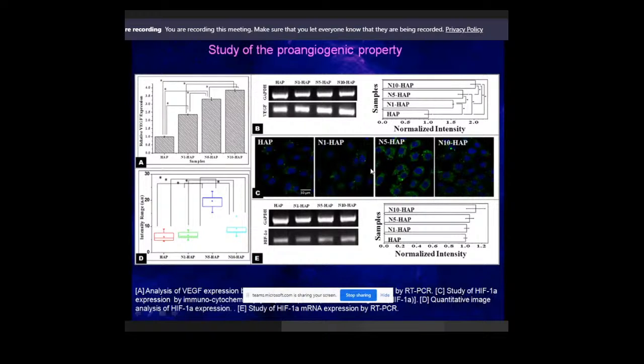And similarly, when we checked the upstream signaling, we found that HIF-1 alpha production also increases. So these two confirm that the moment you add that, there will be an increase in VEGF production as well as in the HIF-1 alpha pathway. Then we check how these materials command the endothelial cells to form tubes.